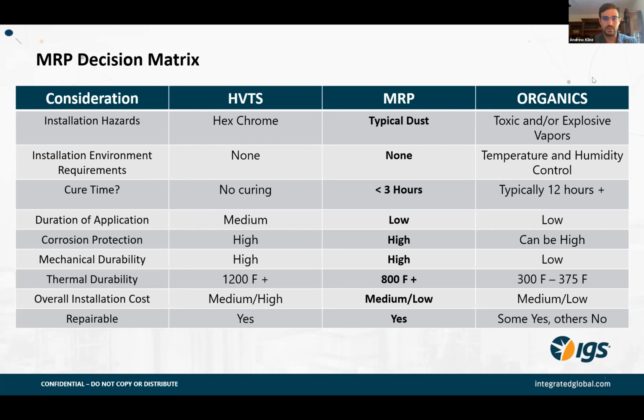Looking at the technical advantages, though, and decision processes, the one that stands out the most is really the ability of MRP to handle higher temperatures than the organics that are out there. Typically, organics are really limited at 300 to 375. They can go to a slightly higher excursion temperature for a period of time, but you do risk the charring during that. And with thermal cycling, because your substrate and your coating grow at different rates over time, with those thermal cycles, it can cause some delamination or cracking or porosity to occur in that coating, which then leads to a coating failure as the corrosive media gets behind it.